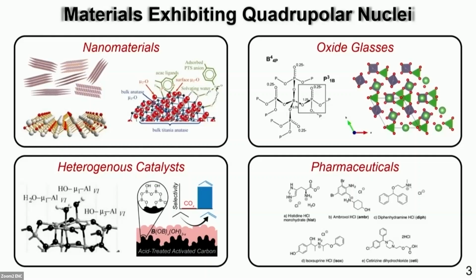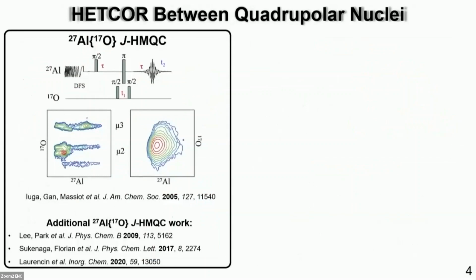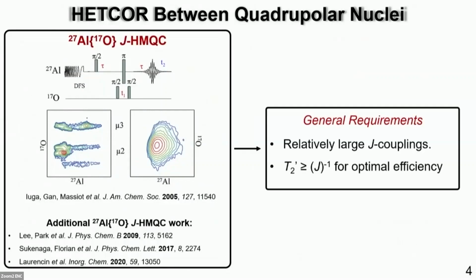These types of experiments have been done before, and the simplest example is a J-HMQC, which was demonstrated by Massiot and Gan in 2005 for aluminum and oxygen. This is the simplest case because no radio frequency pulses are required, so it is directly analogous to your spin 1/2 system. However, these require relatively large scalar couplings and transverse relaxation constants that are greater than the inverse of the J coupling for optimal efficiency. And as I'll show you today, we are interested in boron and oxygen, and these J couplings are very small. Therefore, we want to utilize the dipolar interaction.